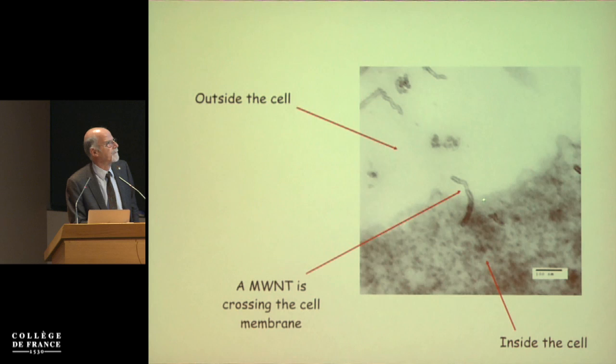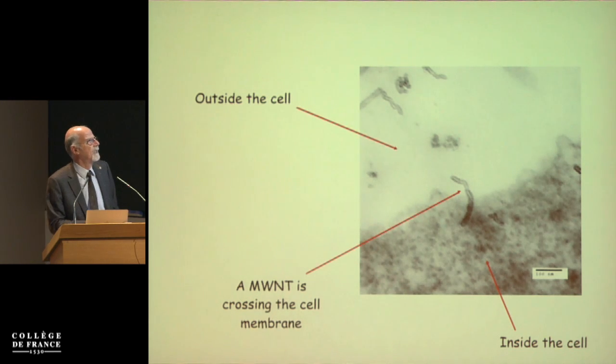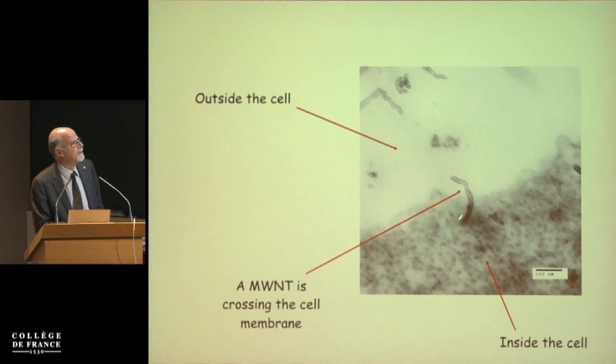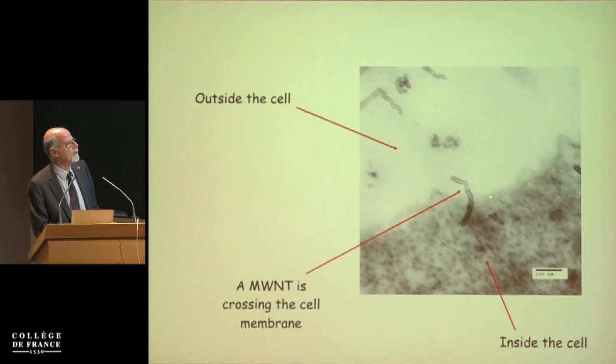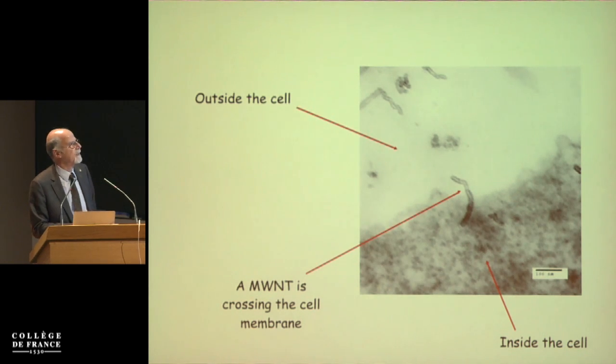penetrating inside the cell. And so here you can see this is the cell membrane, this is inside the cell, this is outside, and we can clearly see that the nanotube is penetrating the cell wall without disturbing in what we have called needle-like mechanism of entering the cells.